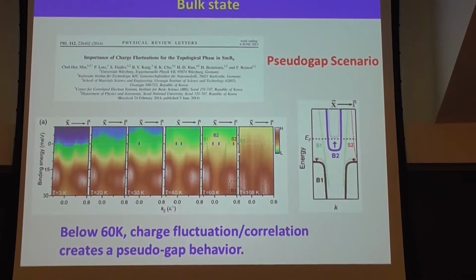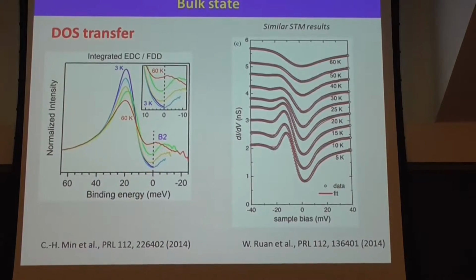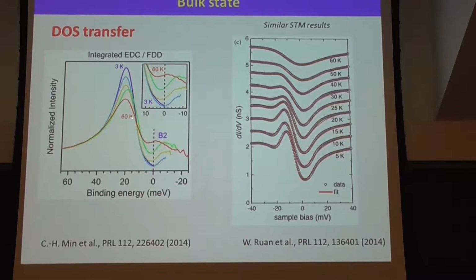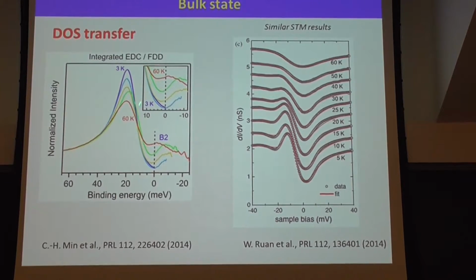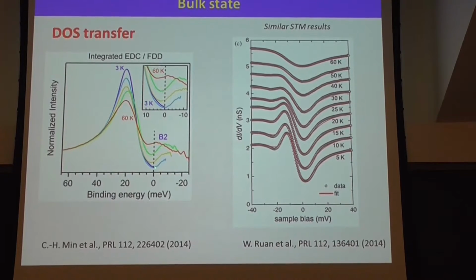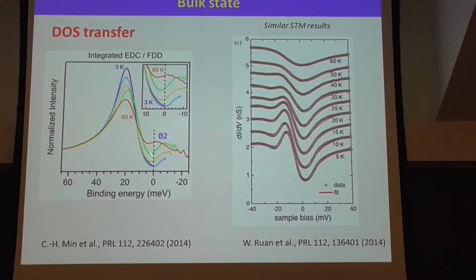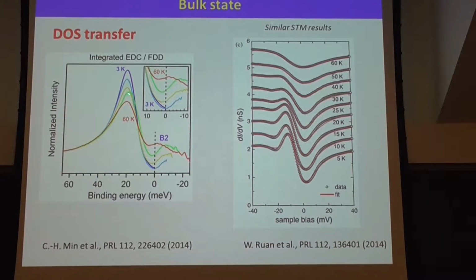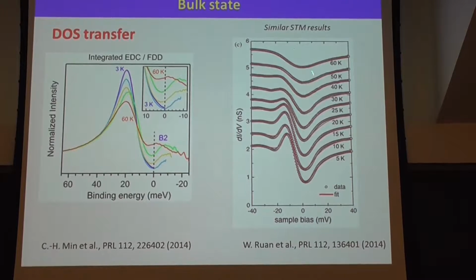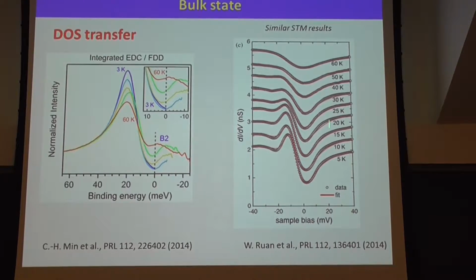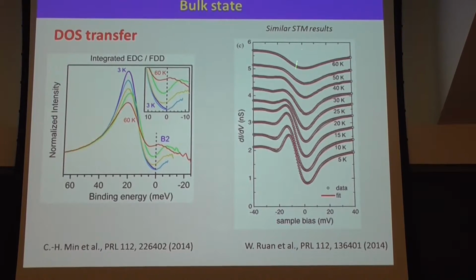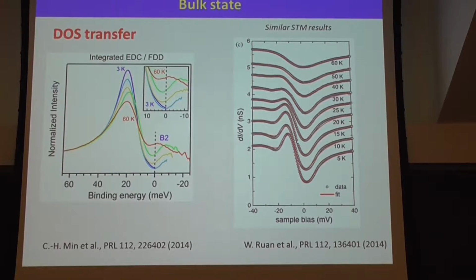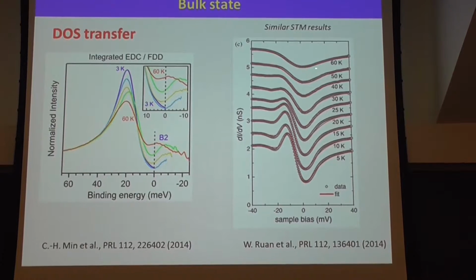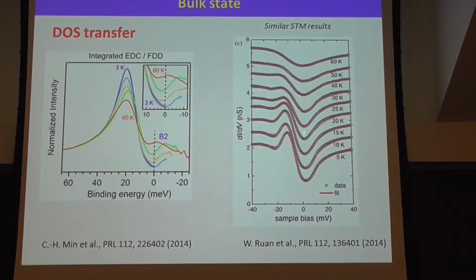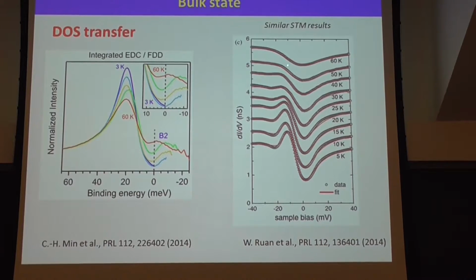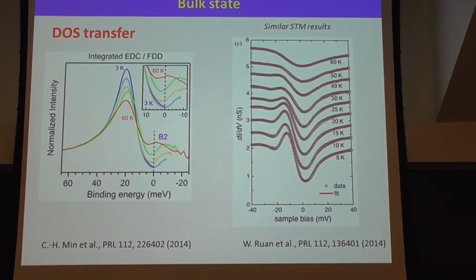In this region, the gap and also the spectral weight is transferred. Also for the EDC, you can see from 60 Kelvin to 3 Kelvin, the spectral weight is transferred from the Fermi level to here. And also our collaborator W. Ruan, by STM, also shows the same behavior. At 60 Kelvin it looks like some dip gap is here. Decreasing the temperature, this gap deepens and the spectral weight increases.